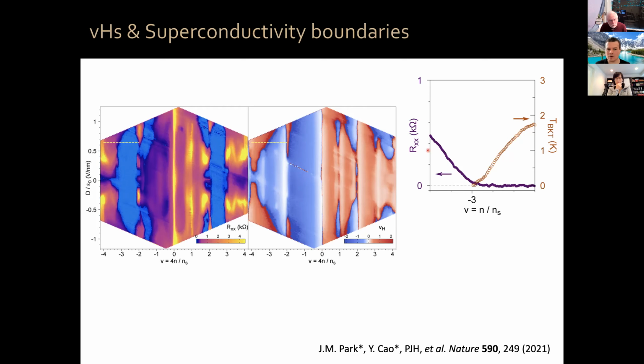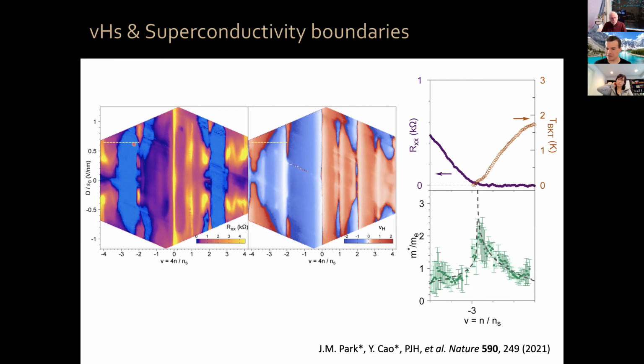Okay, now along this trace we can measure also the effective mass of the electrons, by measuring the temperature dependence of the Shubnikov oscillations. That effective mass is proportional to the density of states in the system. That's plotted here, the effective mass as a function of filling factor along that trace. You can see that as we approach this region, the effective mass diverges. Okay, in fact, this point coincides with that Van Hove singularity that we have here, where your density of states is expected to diverge. Okay, and what you can see very interestingly is that superconductivity ends at the Van Hove